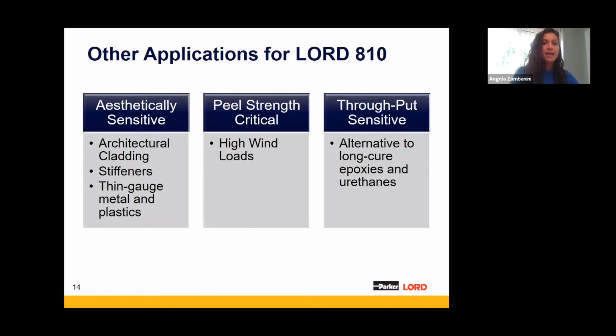Another application for the 810 is in areas that have really critical peel strength requirements, such as high wind load applications. The wind puts the bonded area into peel, which is not great for adhesives, but with a really flexible and strong adhesive, the 810 does really well there. You can also get throughput improvements, so any areas where you need a faster cycling time, the 810 works really great there as well. I have a great case study about improved throughput that I'll go over in a couple of slides.